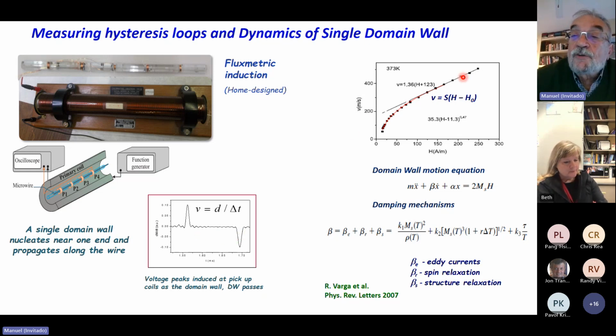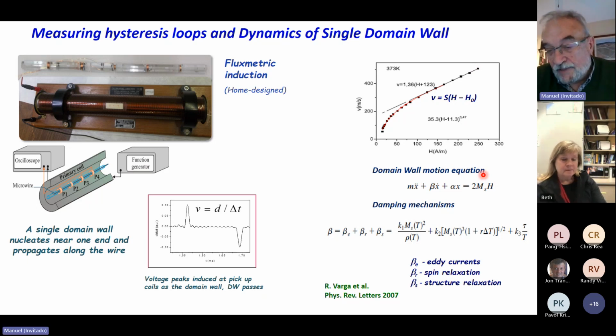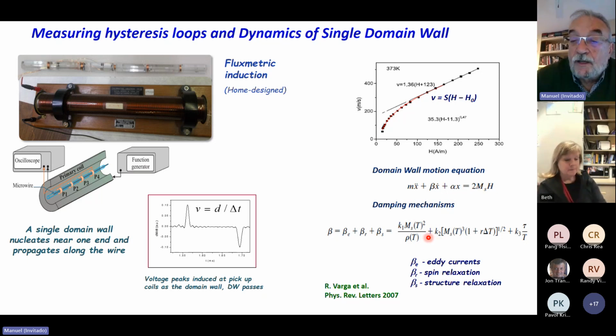Here is a plot of the velocity as a function of the applied field. After an initial transient behavior, we observe a linear behavior of the velocity, which in this particular case has a maximum of 500 meters per second, but can go up to a couple of kilometers per second. So years ago, we studied the dynamics of the domain wall using this general motion equation, and we determined the different damping mechanisms for the motion of this domain wall.